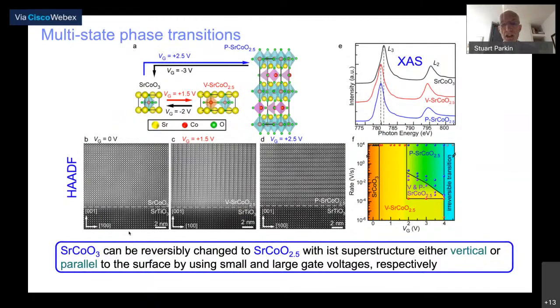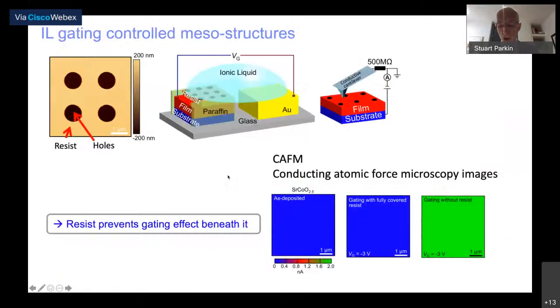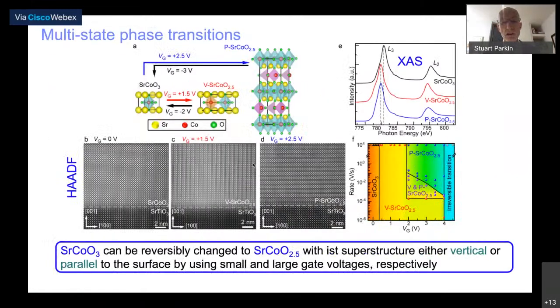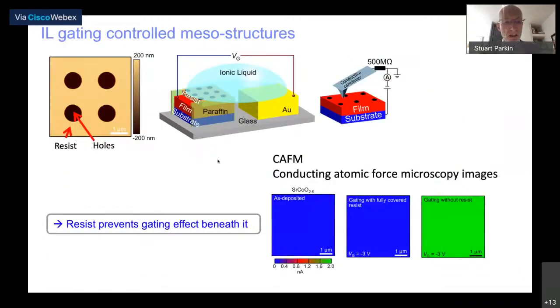Just another point: if we start with the perovskite, shown on the left in B, it's cubic. Depending upon the gating voltage, we've discovered we can make a brownmillerite with a vertical orientation of the layers in which the oxygen is removed, or they can be horizontal, depending upon whether the gating voltage is low or high. Liquid gating causes removal of oxygen vertically or horizontally. I'm telling you this because we want to use it to create spin textures.